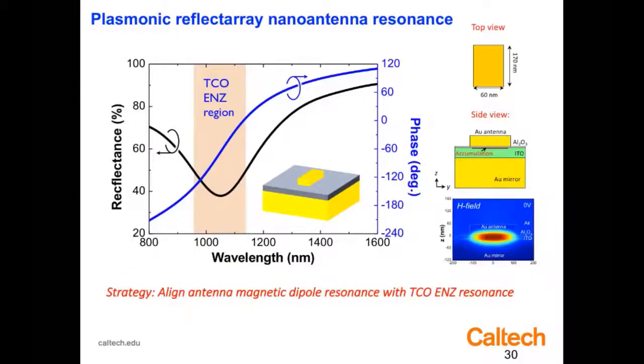So here's how it works. The antenna is this little block of metal. Here's the transistor-like structure where we accumulate and deplete the electrons. If we look at the electromagnetic mode at resonance, there's a so-called magnetic dipole mode that's squeezed in. I showed you how we can squeeze modes into a gap. We're doing the same thing here. We adjust the resonance by changing the geometrical properties to exactly overlie the wavelength range where the permittivity crosses zero, the epsilon near zero regime. In that regime, where we tune the carrier density a little bit, we can produce relatively large phase shifts and changes in the amplitude at optical frequencies.